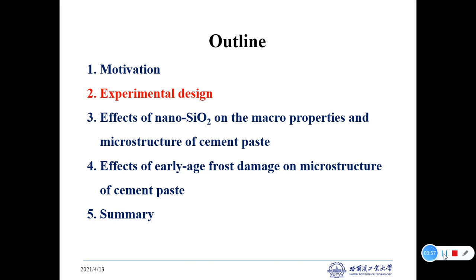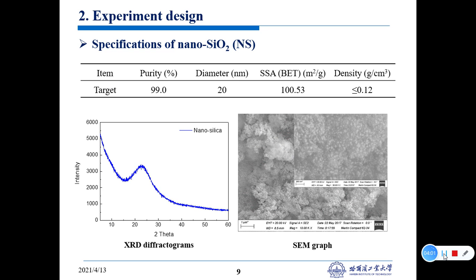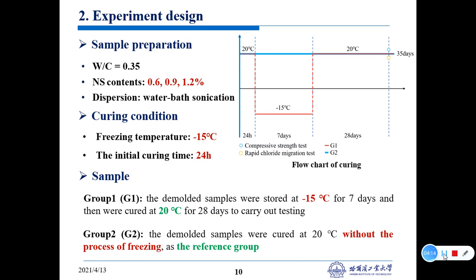The next one is experimental design. This is the specification and information of nanosilica, and it is also characterized by XRD and SEM. This is the sample preparation. The water cement ratio is 0.35, and the contents are 0.6, 0.9, and 1.2%.